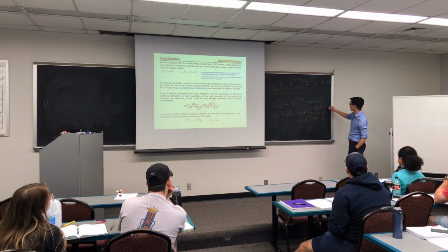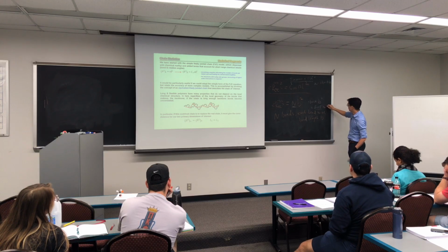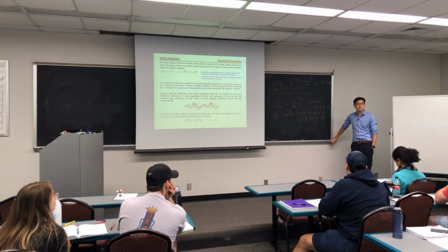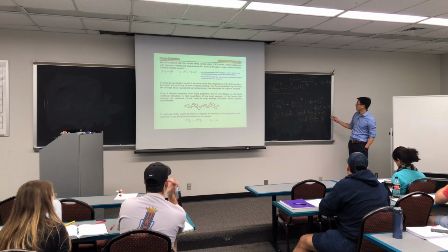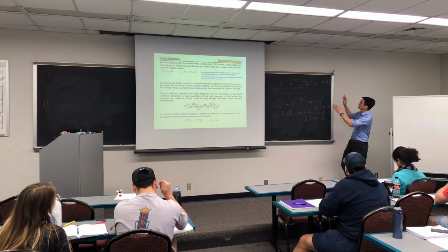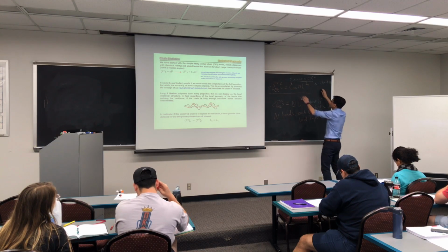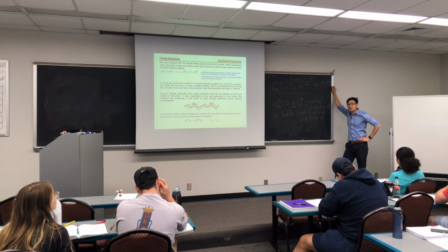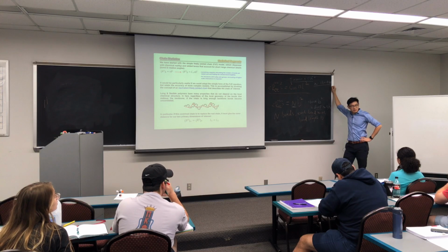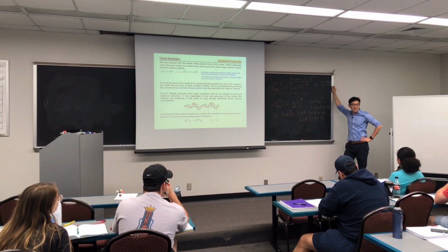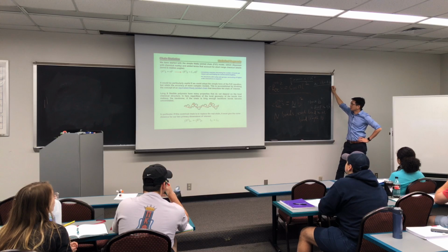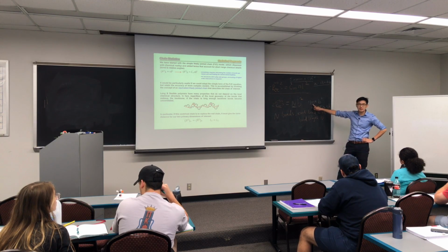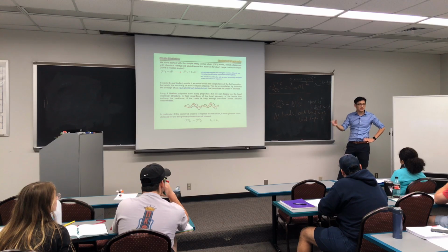So if you multiply by this, I would just do the math here. Let's say it's about 5 angstrom. So what this tells you is that if you describe the same polyethylene chain with a molecular weight of 28,000 in a hindered rotation model, it's equivalent to a freely jointed chain model with fewer bonds, 1,000, and each bond is bigger in terms of size.